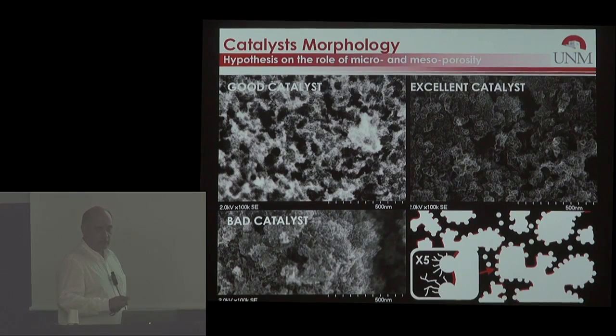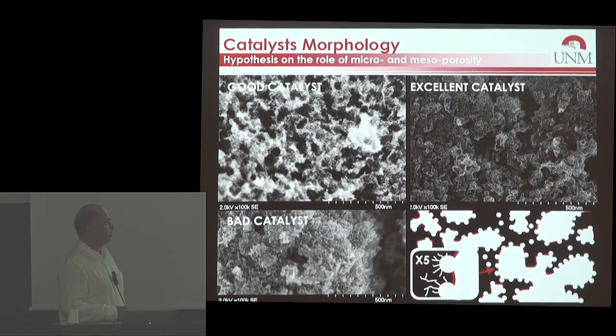What is very important to note is that the practical implementation of these materials in fuel cells depends on the pore size distribution. And here are three catalysts that are chemically indistinguishable. They have the same spectroscopic signatures, the same content, and the same performance in rotating disk electrode. But when you start making MEAs with them, this one is fantastic, this is okay, and this doesn't work at all. The main difference between these catalysts is the amount of the micropores. And that appears to you as the fuzziness of the image, doesn't it? Like a sharp contrast, a high-fidelity image, and this looks like something fuzzy.